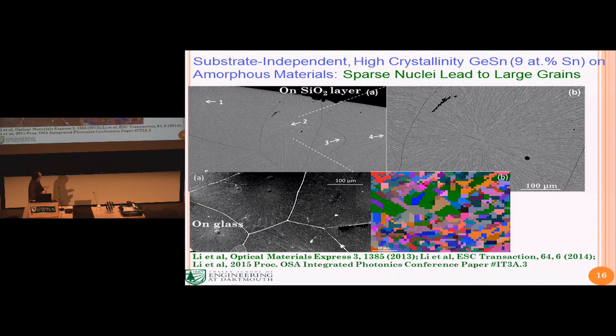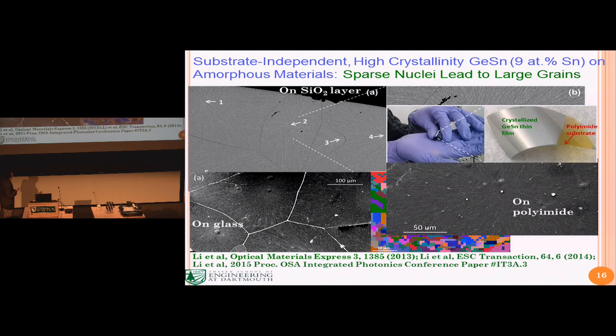Okay, there we go. So we also proved that if you change the substrate to glass or even polyimide, the same kind of growth pattern will hold. So this kind of crystallization is really independent of the substrate. And this is actually the handiwork of Haofeng Li, my student. This is a deposition on plastics, in this case, polyimide. You can actually do this on a flexible substrate with high crystallinity germanium tin. And that provides a very nice template for future high-efficiency solar cells.